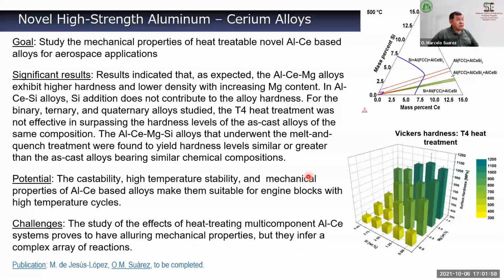At some point, we were connected with Oak Ridge National Lab and with EC Industries. That's a company in Wisconsin. They were interested in promoting the use of a new type of aluminum alloys containing cerium. The reason is that cerium is a side product of the exploitation of the mining, I would say, of rare earth. And cerium has no application whatsoever in high volumes. So the material is just waste. And someone came up with the idea of making these aluminum cerium based alloys at some point. And the idea caught on because once you cast the alloys, they don't require heat treatment to have a high hardness and high ductility.